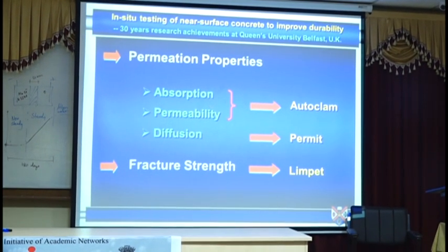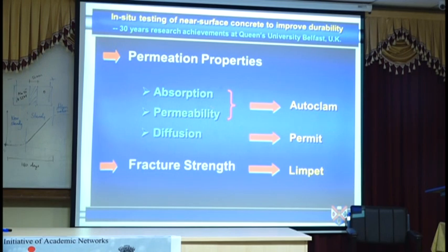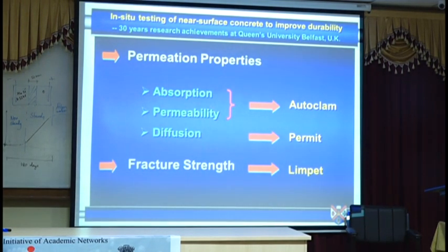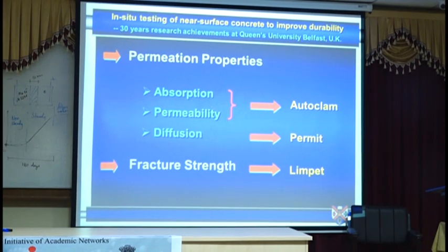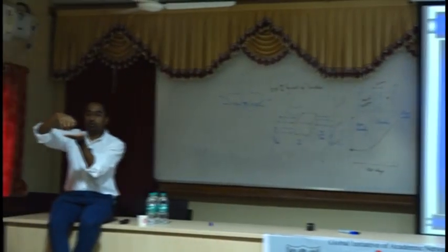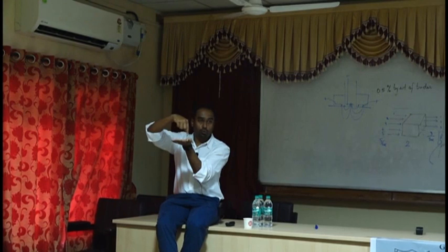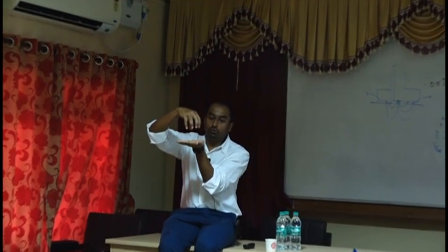What they did is they drilled a core just so that you reach the parent layer or the bottom layer. Then they attached the disc on the surface. Visualize it. Yeah. So it's your original surface here. You put your tile or something else on the top. You wanted to know the bonding between the tile and the parent concrete. So you drilled using a core all the way down to the surface of the parent material. You put the disc on the top of the tile.